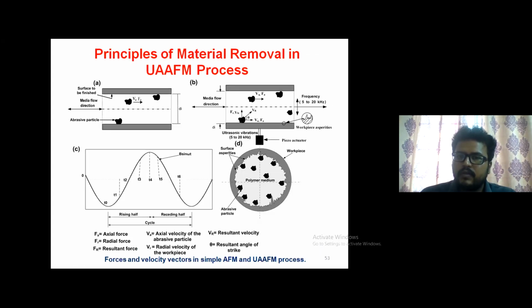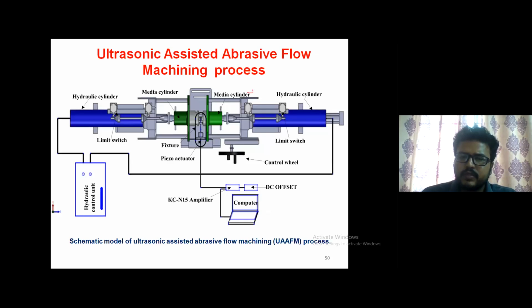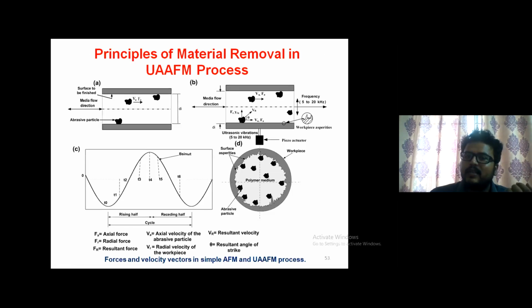So you can see in the figure, this is the media flow direction. It's a horizontal AFM, and we are fixing the actuator radially, perpendicular to the media flow direction. Whereas if you change the actuator position and vibrate the workpiece in the axial direction, then there is a change of the process response. So what are the new parameters added again in my process? Ultrasonic frequency, amplitude, and also the frequency in radial direction, the actuator setup in radial direction and the actuator setup in axial direction. See, we are getting a lot of factors. We are getting a lot of addition of the factors.